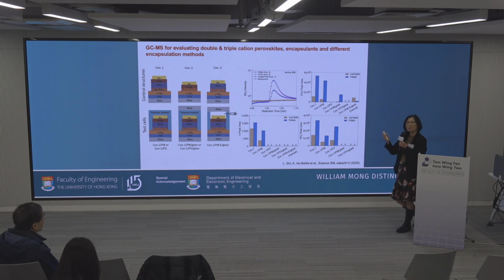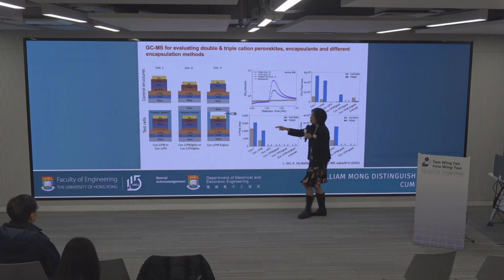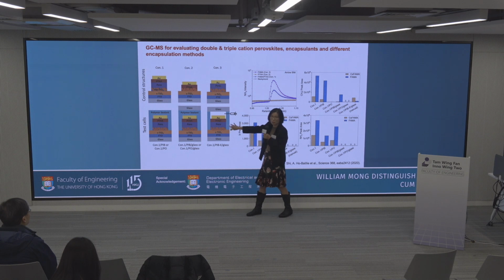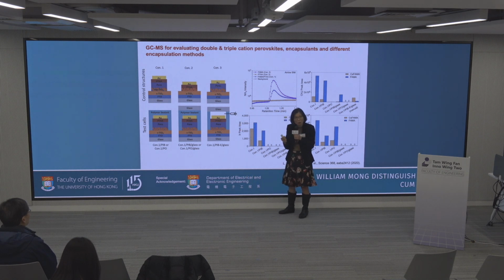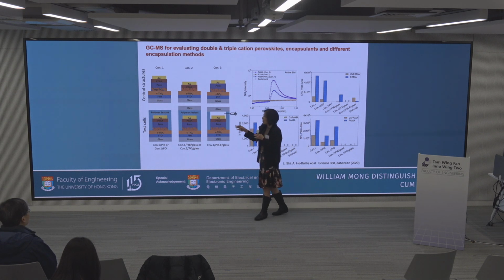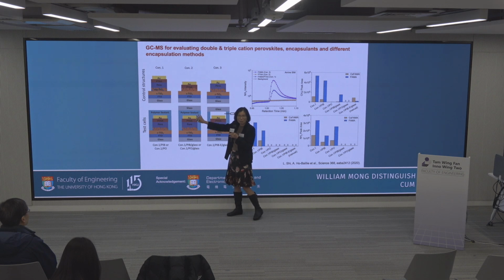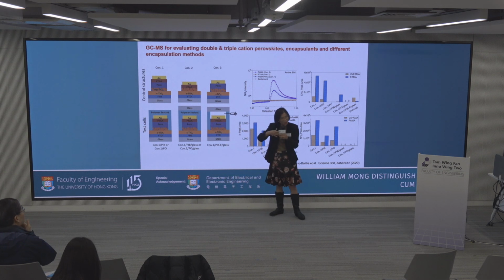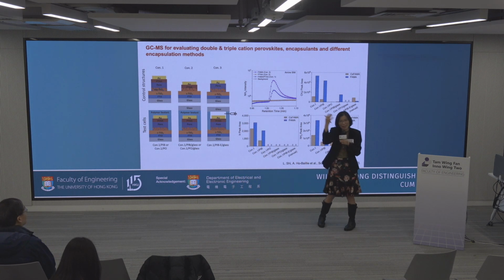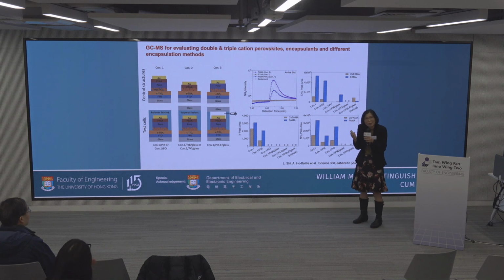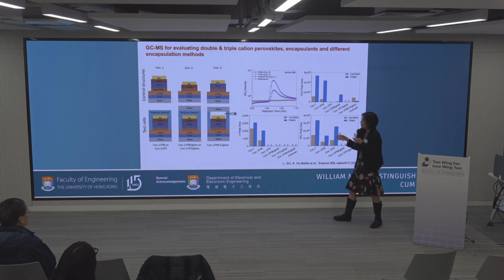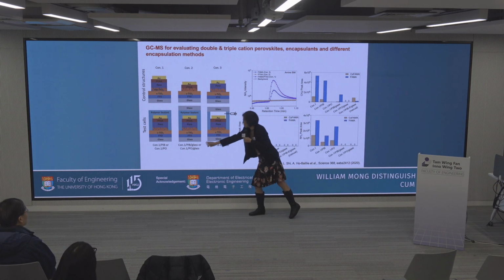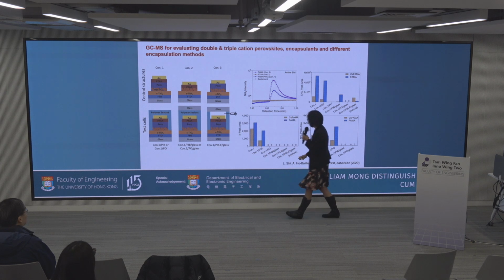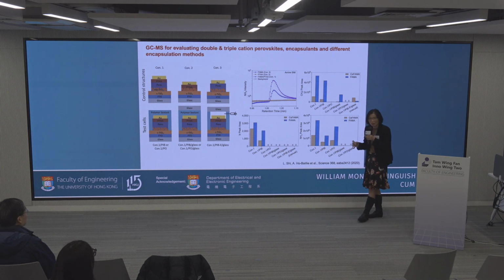Okay, so what does it mean in terms of encapsulating the cell? We looked at two different schemes. There are groups where they just put the PIB on the edge to stop the moisture ingress. But you can also borrow the idea from laminating two pieces of glass, like the double glazing that is used in Europe. So it's like a blanket, so we call it a blanket. We compare the two, and we also compare PIB and POE in terms of the outgassing.